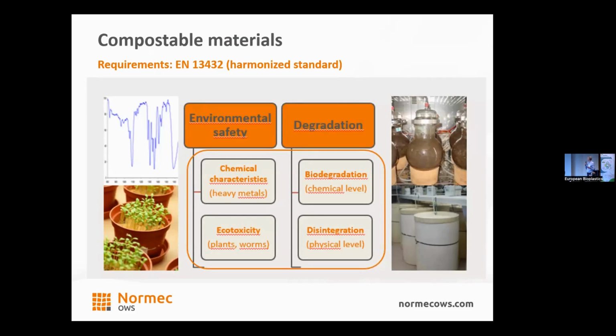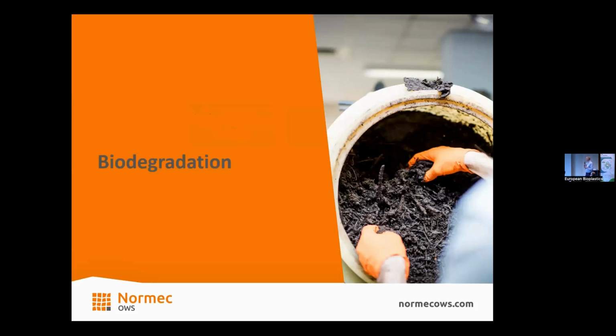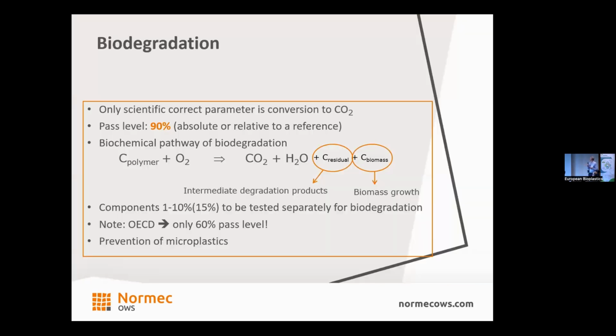For EN 13432, you have only to do plant testing and no worm testing, but this is asked for other standards like in Australia. And you have two characteristics for degradation. First of all, you have to demonstrate that your material is fully biodegradable. Really on a chemical level, the carbon of your material should be converted into CO2. And the disintegration should be sufficient that your material is not visually disturbing your compost at the end of the test.